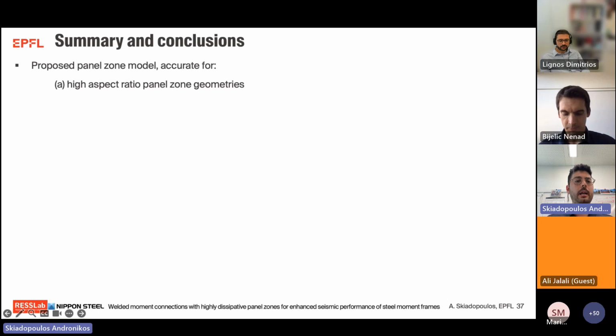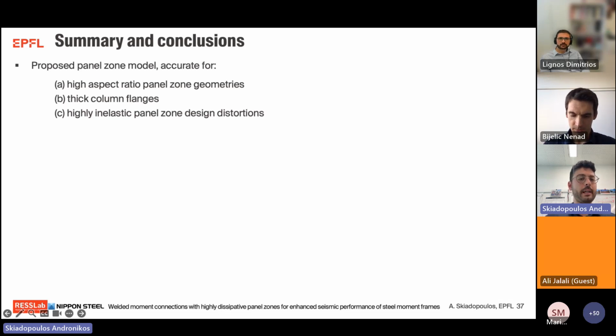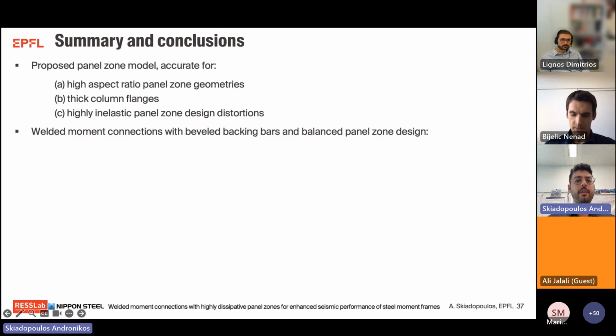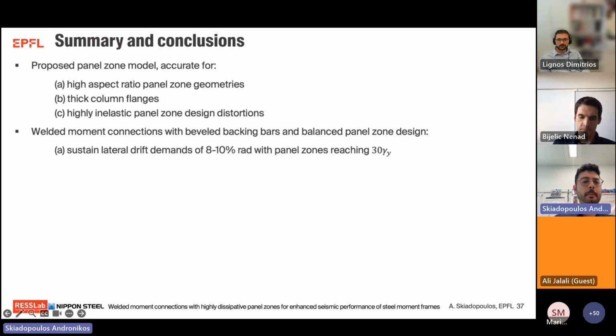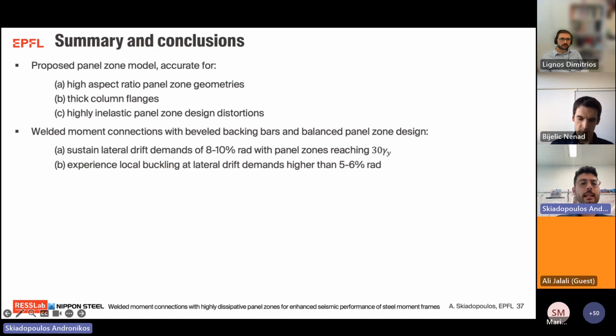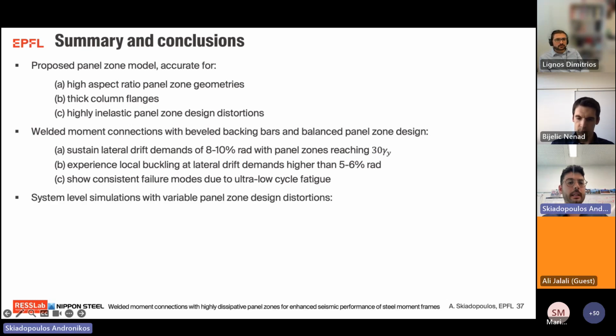To summarize, we proposed an updated robust panel zone model that is accurate for high aspect ratio panel zone geometries, thick column flanges, and high inelastic panel zone shear distortions. Then we proposed a welded moment connection typology with bevel backing bars, so simplified weld details, and a balanced panel zone design that is able to sustain lateral drift demands of 8 to 10% radians, with panel zones reaching even 30 times the panel zone shear distortion at yield. These connections experienced local buckling at lateral drift demands higher than 5 to 6% radians. And what we saw is a consistency in the failure mode that involved cyclic fatigue.